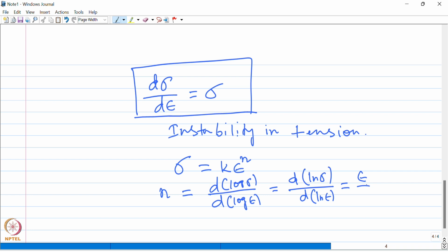That will give us this expression in terms of d sigma by d epsilon, and by rearranging we can also write that d sigma by d epsilon is equal to n into sigma by epsilon. Okay, and now if we put this into the instability criterion, then this is what we will get. Okay, so this is our instability criteria. And now we have got d sigma by d epsilon is equal to n into sigma by epsilon. So from here we can get the true uniform strain at which the necking will begin.